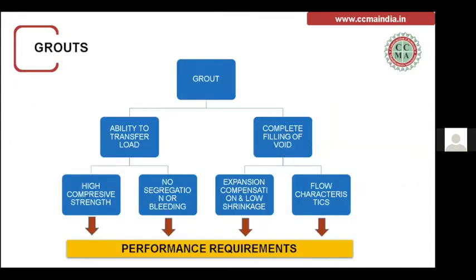But when we select the grout, we should have some level of performance from the grout. It should be able to transfer the load successfully without disintegrating, cracking or failing under compressive loads. The next very important thing is complete filling of the void. There should not be any gap developed. There should not be any shrinkage because of bleeding or lack of flow when there is heavily congested reinforcement. So it should fill up completely.